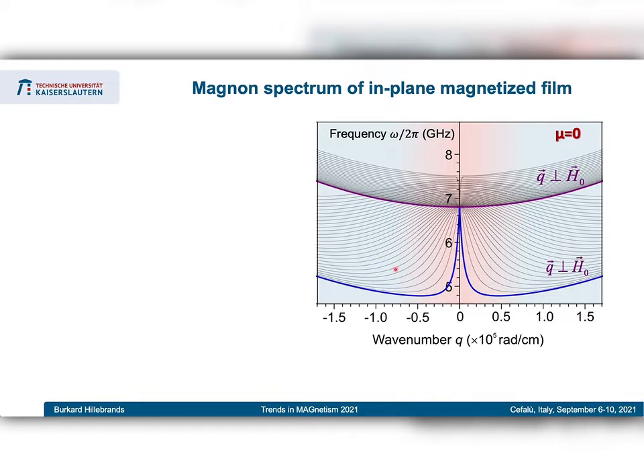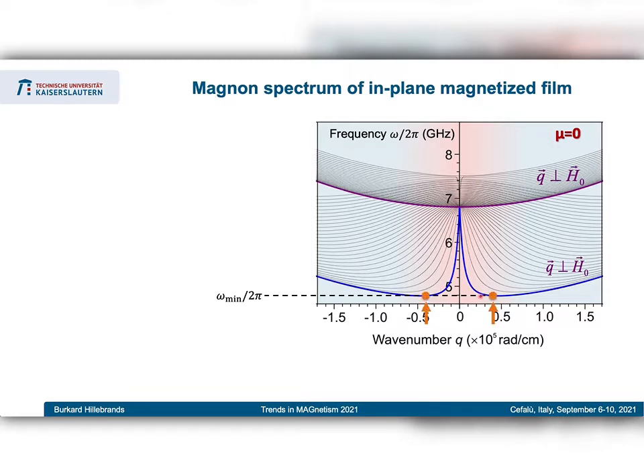You also see many black lines in this diagram. These are the so-called standing spin waves — modes which travel back and forth between the two sides of the film. Due to the finite thickness, typically a couple of micrometers or less, they form a set of discrete modes. If the mode spacing is very narrow, you can consider this a continuum of modes. We plot the dispersion for both positive and negative wave vectors, giving two minima. These minima are very important for us for the Bose-Einstein condensate, because the condensate forms exactly at the minima.